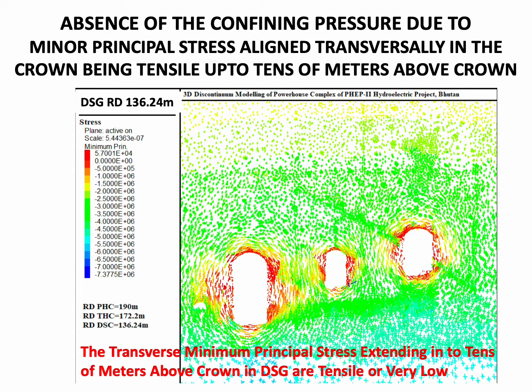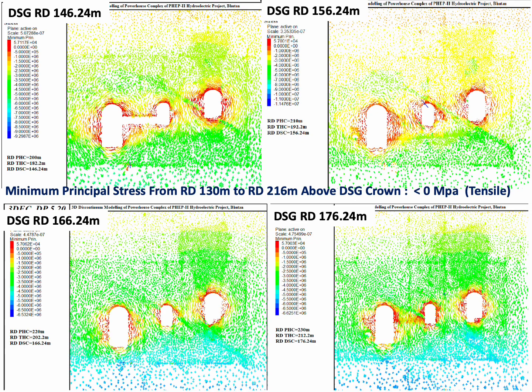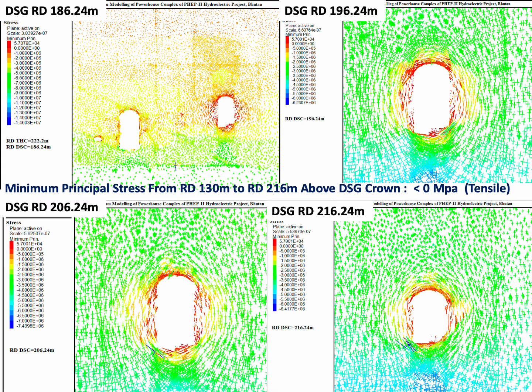They are either very low and negative, or are 0 above the crown and around also. This also shows that over the reach from 146, 156, 166, 176, all across, the stress conditions, or the minimum principal stresses, were similar, and they were all tensile, extending into tens of meters above the crown. Also further 186, 196, 206, 216, everywhere the confining stresses were missing and they had become tensile.